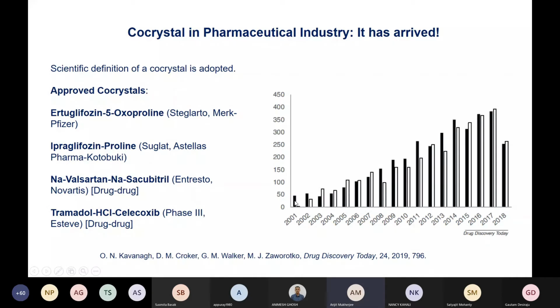It shows that it's clearly increasing over the years, and now we have at least four approved co-crystals: of Ertugliflozin-5-Oxoproline, ipragliflozin, and then Entresto and the tramadol HCl-celecoxib co-crystal. Interestingly, the last two are drug-drug co-crystals. And what illustrates the importance of co-crystals in pharmaceutical space is the case of Ertugliflozin-5-Oxoproline, where the main compound was amorphous, but once this co-crystal was made, it was approved.